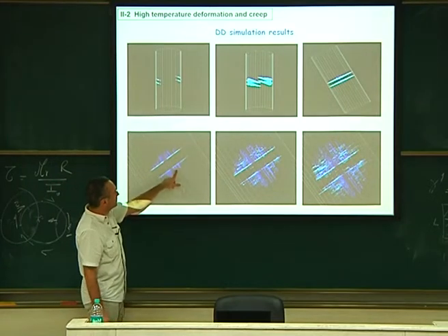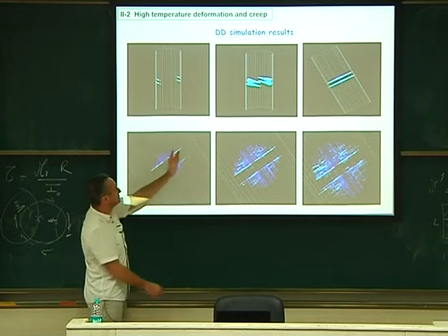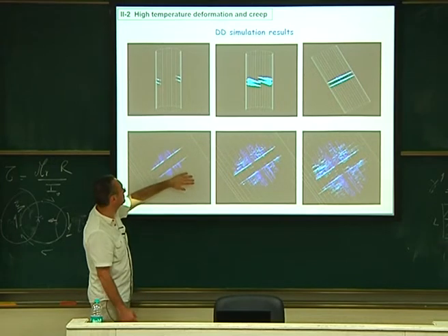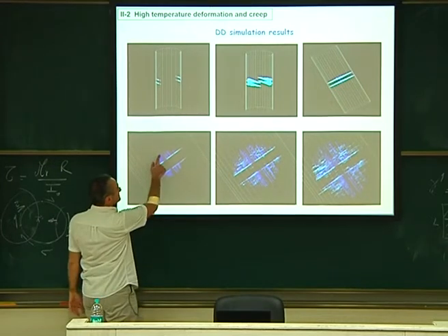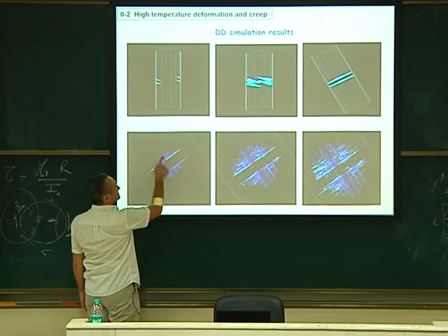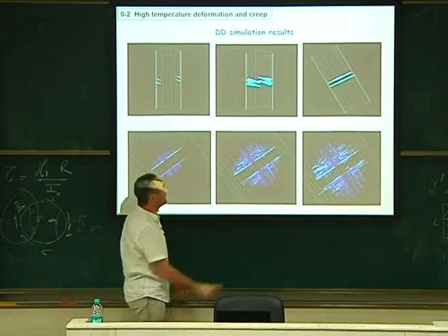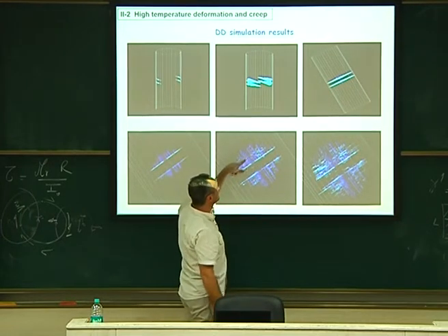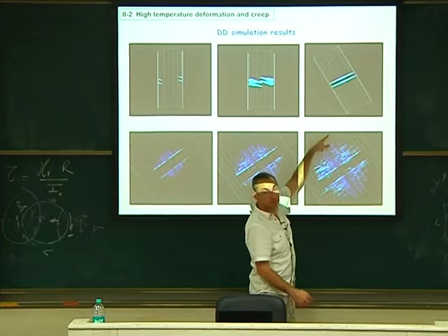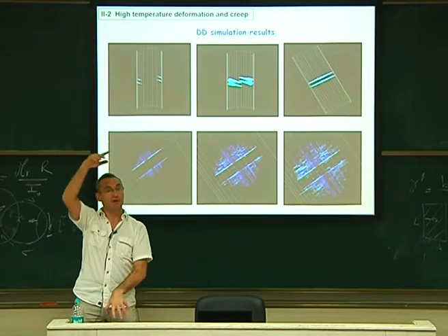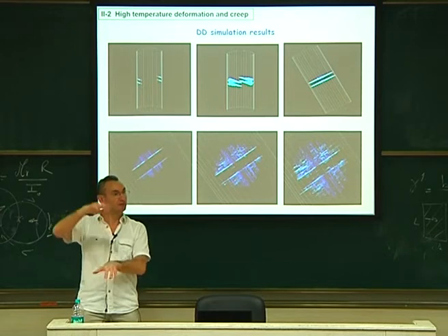Those are the dislocations where they cross-slip, and you can see that they follow more or less the curvature, the profile we saw with the internal stress field in the prismatic system. Here it's longer than here, so here it's easier to move far away than there. Then when they move like this, they want to move back, and you generate new dislocation sources in several planes at a given distance, which will be able to multiply and move further by cross-slip and so on. So you can invade your full specimen just by the cross-slip mechanism. Even if you start with a single source, you may have dislocations everywhere, step by step, plane by plane.